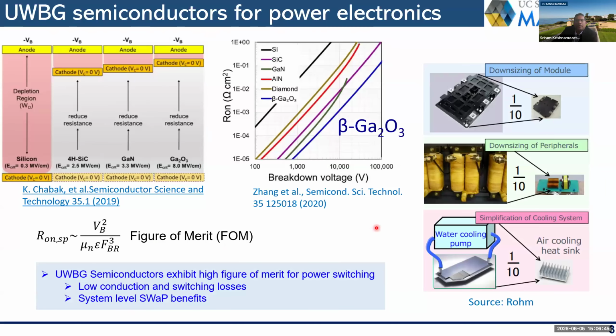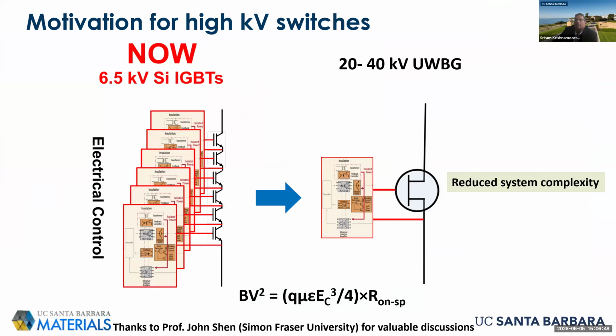So before that, I would like to also maybe give a use case or pitch for why we generally need higher voltage switches. So right now, the highest voltage power switch you can get is a silicon IGBT at 6.5 kV, and silicon carbide power MOSFETs, which are at either 1.2 kV or 3.3 kV range. So if you have a high voltage system, then you need to stack multiple of these modules in series and then control them synchronously to be able to realize a high voltage system.